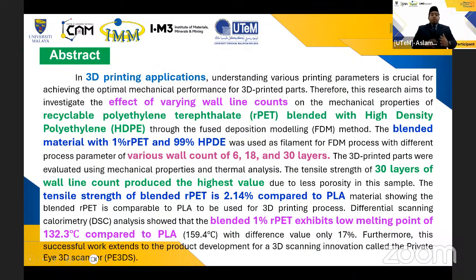Before we dive into what my research is about, I want to give a quick view of it. In 3D printing applications, various printing parameters are crucial to achieve the optimal mechanical performance for 3D printed parts. Therefore, this research aims to investigate the effect of varying wall line count on the mechanical properties of recyclable polyethylene terephthalate blended with high-density polyethylene through the fused deposition modeling method. The blended material of 1% rPET and 99% HDPE was used as a filament for the FDM process with varying wall line counts of 6, 18, and 30 layers. The 3D printed samples were evaluated through mechanical properties tests and thermal analysis.